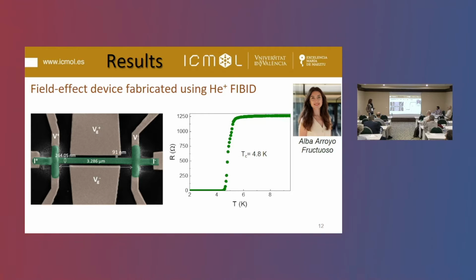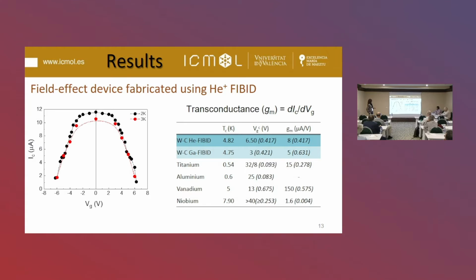In this case, we used a wider wire, and even the separation between gate voltages is at least a bit higher compared with the previous device. And in the same way, we observe the same modulation in the critical current as a function of the gate voltage at different temperatures.